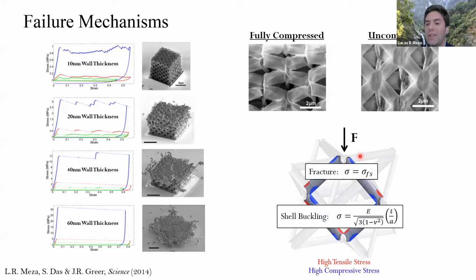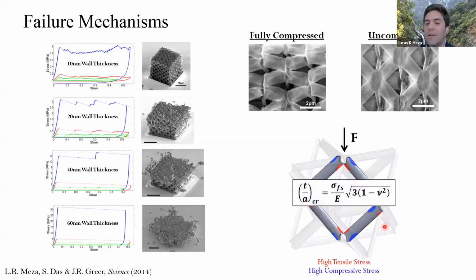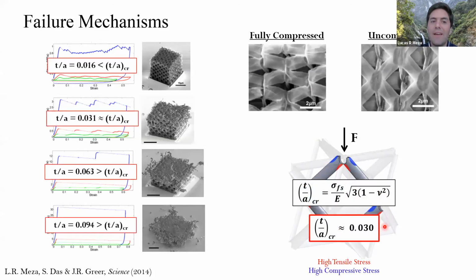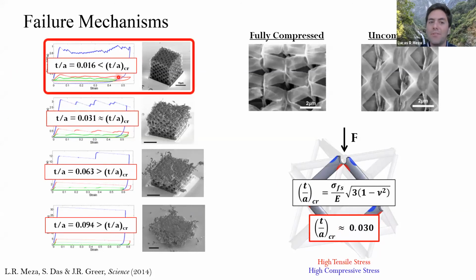You can relate those two — either it's going to fracture or it's going to buckle, and we have a relationship for shell buckling. You can come up with a critical transition point, plug in some material properties, and say anything below that critical transition, i.e. our thin walled structures, will be shell buckling dominated and able to recover. I'll come back to that a little bit later in the talk.